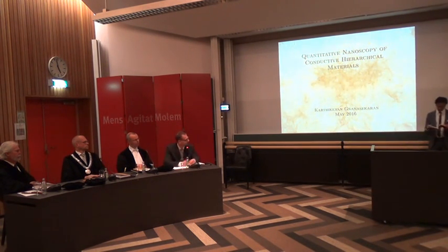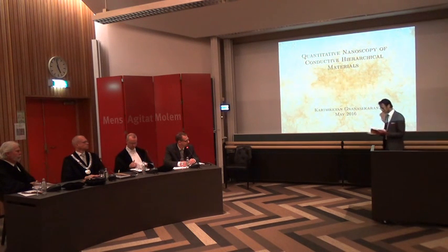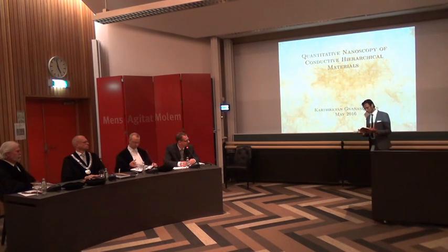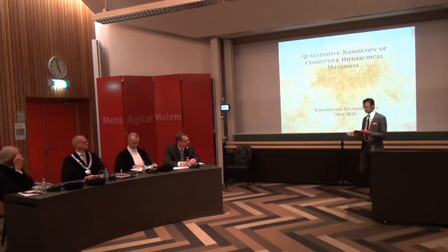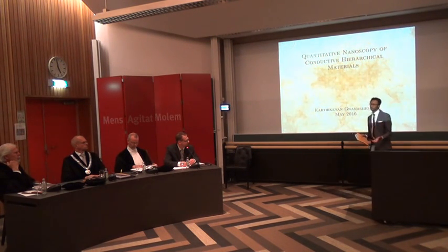Yeah. On page 82, 84, the multi-layers, what I have measured there is, first of all, to analyze quickly whether the processing is good or bad. So that was my motivation in this specific analysis. I tried to measure it by the waviness of the layer, trying to find the defect location and measuring laterally which location has a huge number of defects. But this can be further extended to measure the crystallinity,